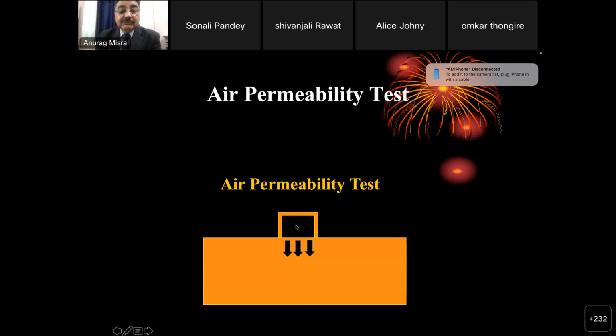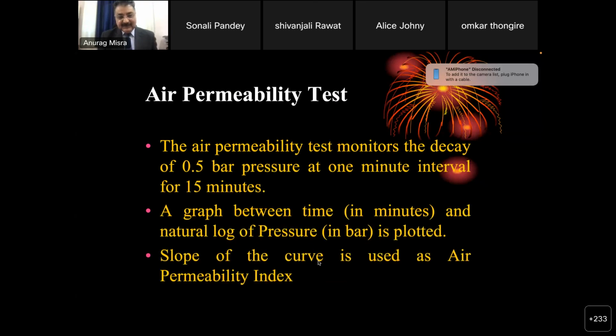So this air which is diffusing through the concrete surface means the pressure is going to drop. Once a pressure of, let's say, 500 millibar is applied and you leave it, the pressure starts to dissipate, which is measured every minute for 15 minutes. Then we plot a graph of the log of the pressure against time, and you get a curve, and the slope of the curve is taken as the permeability index.